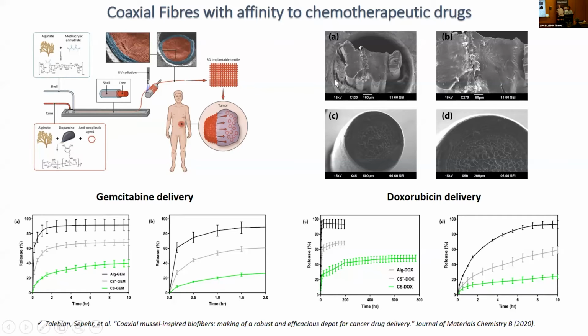So then we make these fibers. Obviously, these are hydrogels we're talking about, and their swelling ratio is significantly high. So we took microscopy images of the fibers in dry state, and in dry state you don't see any porosity, but after they completely swell, you can clearly see the core and shell of these fibers and the different pore size distribution associated with the core or the shell.